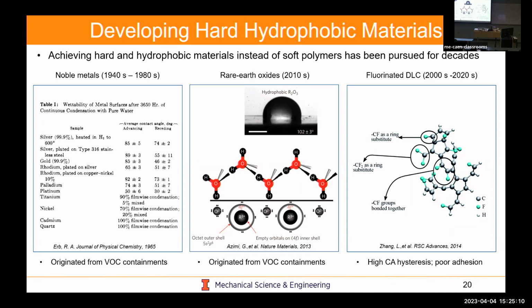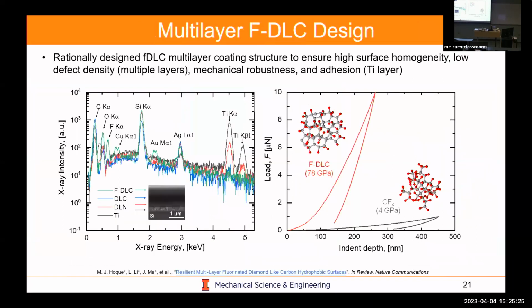You could co-deposit fluorine or hydrogenated chemistries with diamond-like carbon. DLC is actually used as an anti-wear coating in engine applications, so it's already extremely durable and extremely adherent to substrates, especially metallic substrates. And so we started a project by collaborating with a company called Oerlikon Balzers. They're the biggest manufacturer of DLC deposition chambers in the world. And so what we do is we develop a multi-layer coating, which has different constituents.